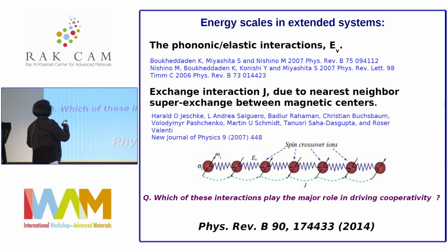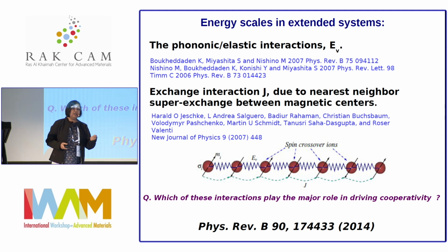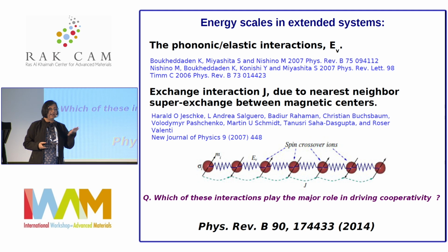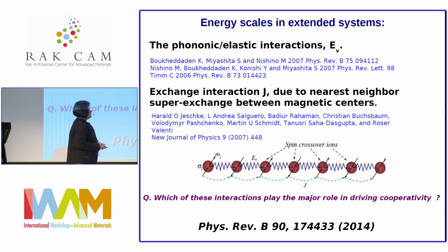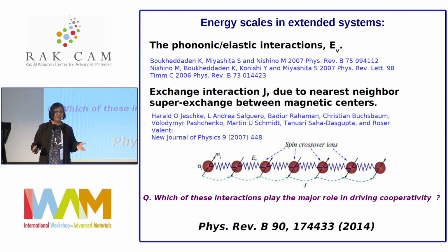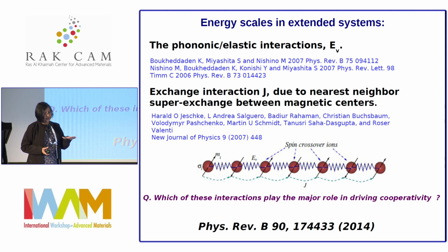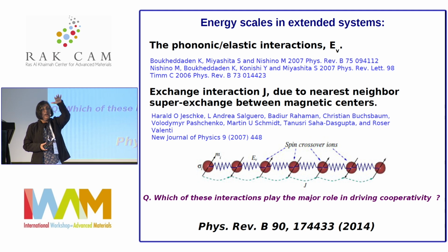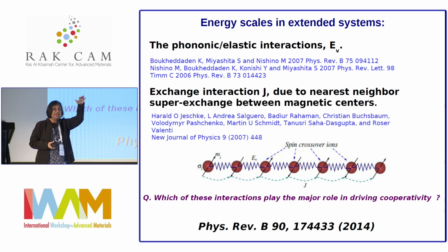The other thing which we talked about is also the magnetic exchange interaction, because when you are at the low spin state, take the example of iron 2+, again, it's a diamagnetic object with no spin, no moment. So therefore, there is no magnetic energy. So you start from a low spin state, heat it up, and go to the high spin state. There is no magnetic energy contributing. But if you are at the other limit, that you start from a high spin state and slowly cool it down to bring it to the low spin state, of course, the system will not like to lose its high spin state, because it will lose that magnetic energy. So it is basically the interplay of these two.